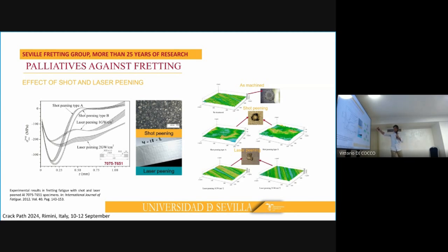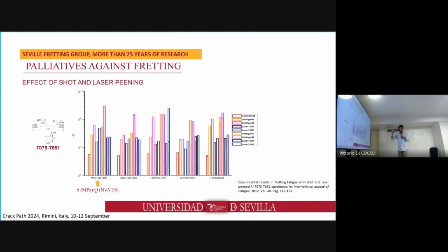Here, we can see some confocal perspective images in different conditions: in the as-machined test specimen, with the shot peened test specimen, and with laser peening. Also, we can see the different fretting scar obtained in each case. After this, we thought that maybe this surface condition and the different fretting scar obtained has an important influence on the fretting behavior.